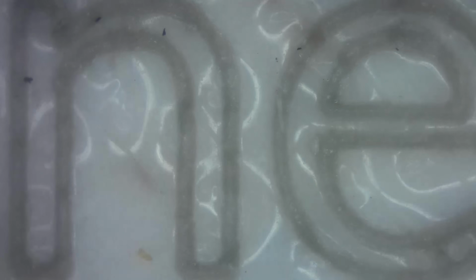One interesting thing I saw under the microscope: on some MOPA marked samples, darker hue samples had larger dark char particles underneath the surface, in contrast to the UV marked samples, which were uniformly darker. So even when both lasers created a visible mark, they don't necessarily create it by exactly the same mechanism.